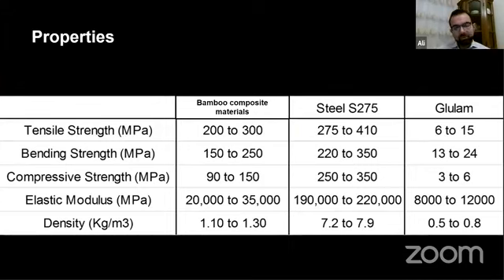These are the properties that we achieved at the end of 2017 based on these tests that I have mentioned earlier. As you can see, in terms of tensile strength, we had a range of between 200 to 300 MPa, Newton per square millimeter. When you compare it with glulam, this is the glulam that is widely available in Singapore.